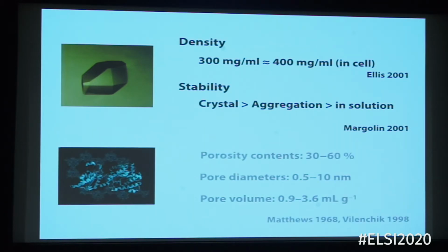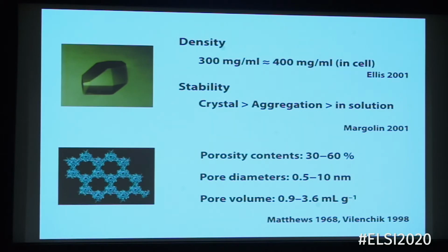That's why when we see the protein crystal as an assembly structure like this, it has a very unique internal porous structure, like typical porous materials such as zeolite, mesoporous silica and MOF. So I show here the very unique porous property. These porous properties are comparable to those of typical porous materials. That's why we can modify the porous protein crystal like zeolite or MOF or other typical porous crystals. We can expand and combine the catalytic activity of the protein inside the crystal to any kind of application.